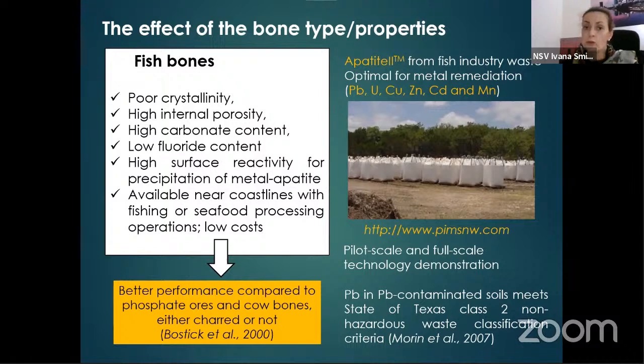Then the effect of the bone char depends on the properties of the bones, and a great difference was detected between fish bones and the bones of other species that were examined, for example, cow bones, pig bones, or chicken bones. Fish bones exhibit especially poor crystallinity and especially high internal porosity, which make them very reactive, and this induces the precipitation of metal apatites.